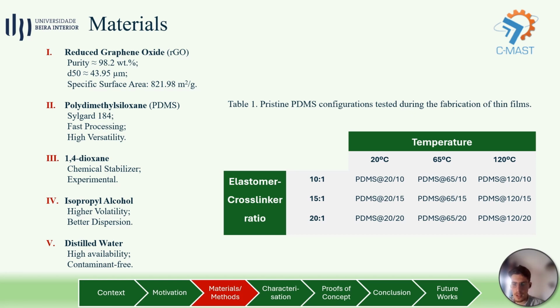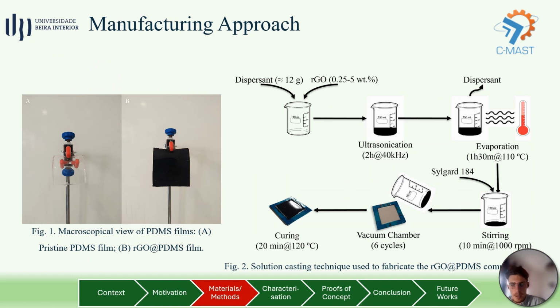Similarly, despite multiple elastomer-crosslinker ratios being tested, only the 15:1 ratio will be considered today, and especially the 120/15 configuration, since this was the best alternative of all, and the one we used to produce our composites. Unlike pristine PDMS production, where only the mixture between the elastomer and the crosslinker was cured, the approach for manufacturing the composite was a little bit more complex and time-consuming, where we decided to integrate elements of both solvent casting and solution casting, followed by a cure at 120 degrees for 20 minutes.